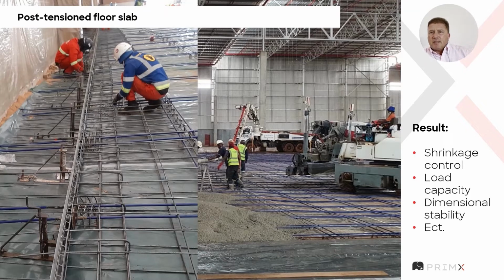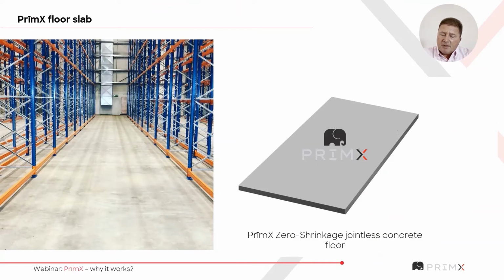Now, interestingly, PrimX floor slabs are predominantly steel fibre reinforced. So what do you think? That's old hat. We've been doing that for 30 odd years, nearly 40 years. Well, we have, that's right. And we've been producing joint-free floor slabs for probably about 35 to 40 years, where the steel fibres are incorporated into the concrete in such quantity that they control the effects of shrinkage. So instead of having to put a saw cut in at about every 6 metres or so, we can let the panel size increase to about 40 metres or thereabouts, and that concrete will simply reduce in volume, and that's great.